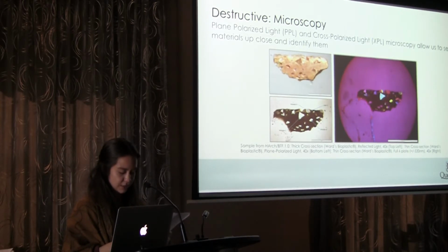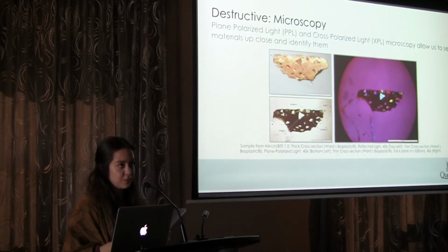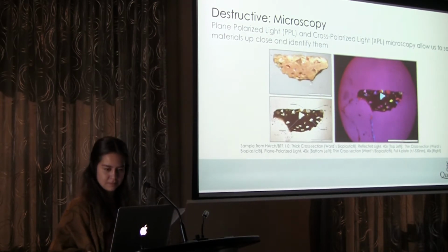Interference and retardation colors of inclusion number 3 indicated the presence of quartz, which we were also able to corroborate using XRD or X-ray diffraction. Lastly, the diagonal orientation of the non-plastic polymineralic inclusions is characteristic of wheel-thrown vessels.